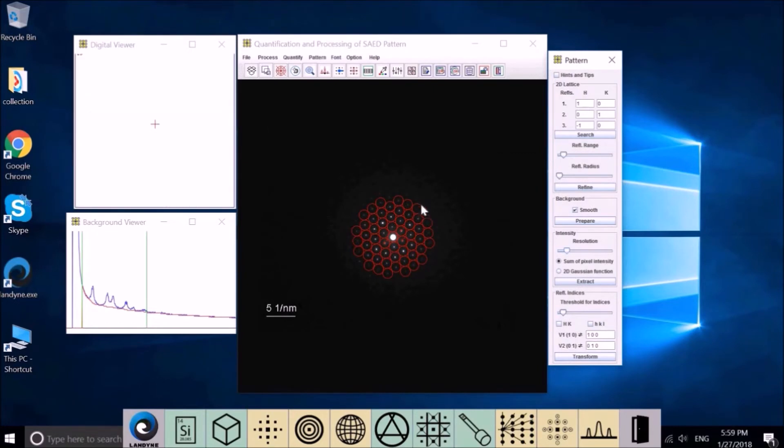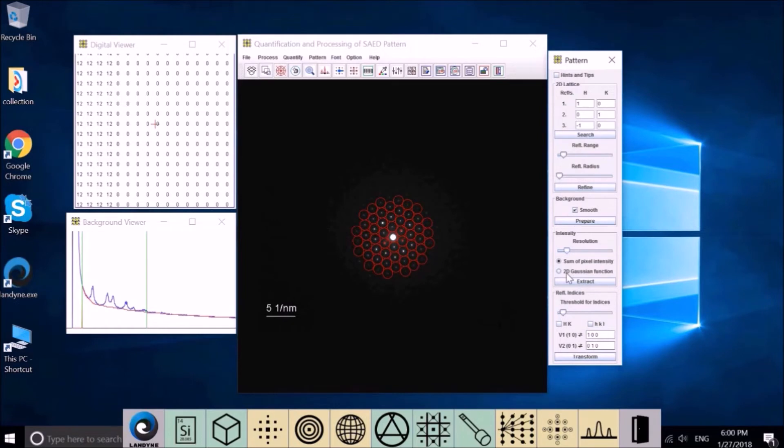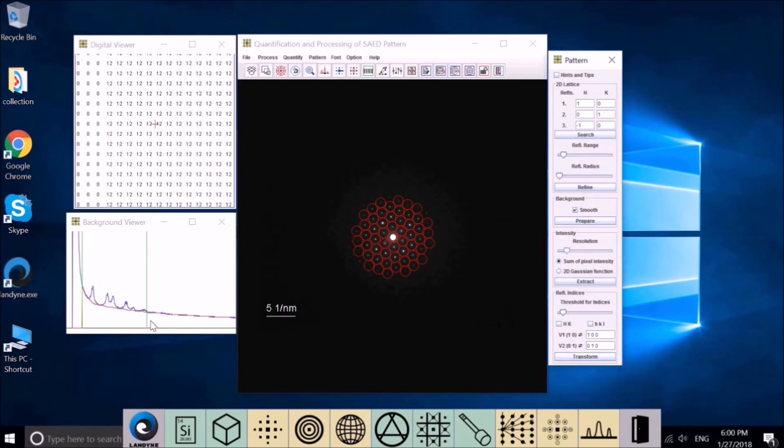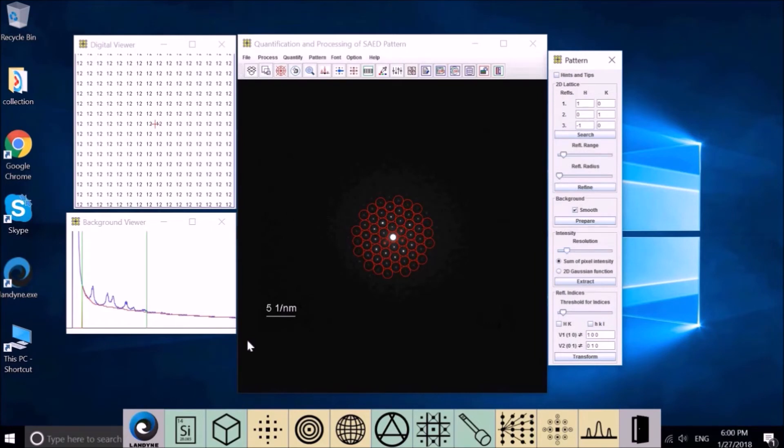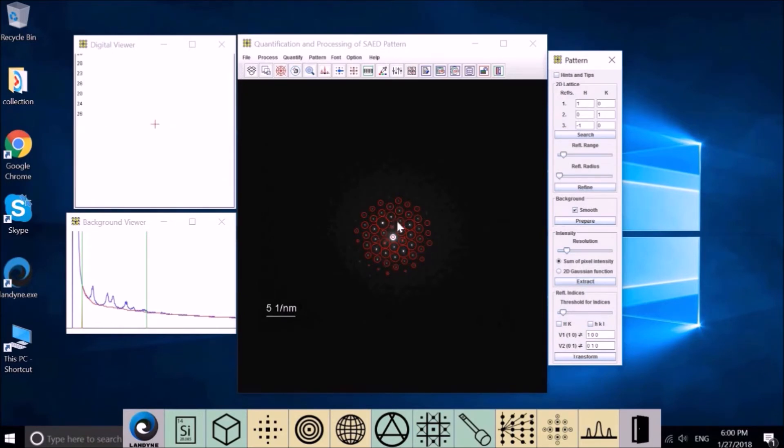In the first case, diffraction intensity is simply sum of the pixel intensity in each circle. In the second case, Gaussian bell shape function is used to restore the peak shape. Diffraction intensity is then calculated from the Gaussian function to compensate the cutoff due to saturation. The background intensity is removed from the same curve in both cases. Diffraction intensity is retrieved for display and can also be saved to HKL intensity file.